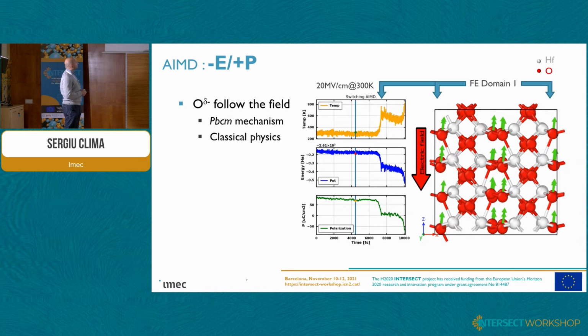What you will see here is basically two ferroelectric domains - one is in the center of the supercell, another one is across this periodic boundary here. So half of the domain is here, half is there. This switching will happen at this 7,000 femtosecond time point, whereas the second domain will switch at the 10,000 femtosecond point.